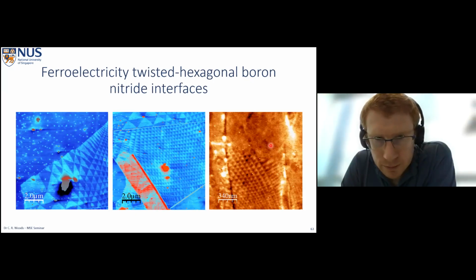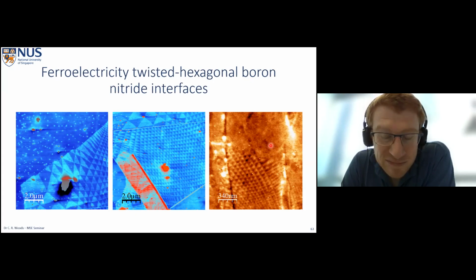So the main difference between these different techniques is the scale, right? Because if you do it in transport, you pretty much probe this moire macroscopically. And if you do it in optics, you have a resolution of, let's say, about a micron. But here you image this moire pattern quite nicely.